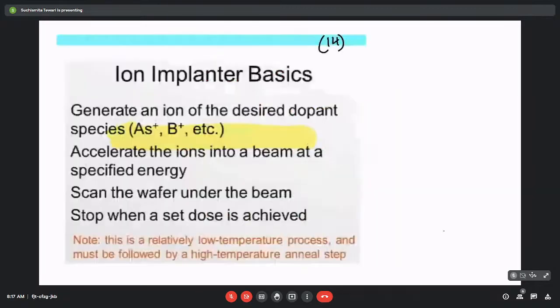So basically, what is that? Now we know the ion implantation mechanism. That is, high energy dopants or high energy ions are bombarded towards the silicon surface in order to dope the silicon. So first of all, what we need to generate is that particular ion. If we want to dope it with arsenic or boron, accordingly we are going to generate that. Then we have to bombard those ions with high energy to the silicon